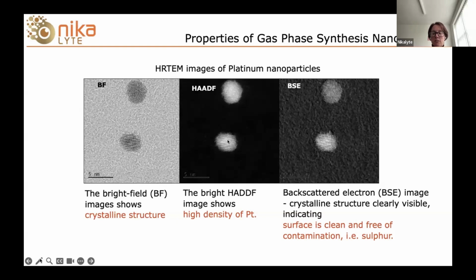In the high angle annular dark field image, you see much the same image, but in this image, the contrast is very bright, which we associate with very dense and high weight materials such as platinum. But the image that's really interesting, and I want to draw your attention to, is this backscattered electron image, the last one. What you're seeing here, the backscattered electrons are only giving information about the surface of the nanoparticle. And what we're seeing in this image is that the crystalline structure is present on the surface of the nanoparticle as well as in the bulk of that nanoparticle. And what that proves to us is that that surface really is clean. There's no sulfur or other contamination on the surface. So it really backs up our claim that this is a very pure and chemical-free technique.